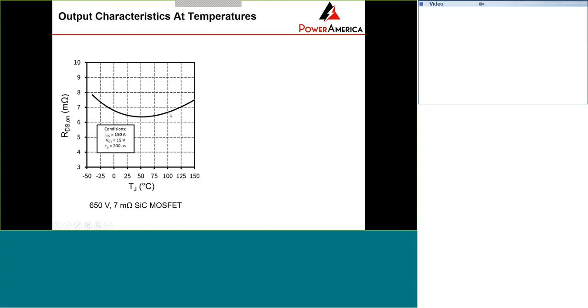And when we increase the temperature beyond room temperature, to 50 degrees C, the resistance increases again because the drift resistance increased and channel resistance reduced at high temperature. But overall, if you compare the resistance at 150 degrees C and room temperature, it is just increased by 15%. So the temperature coefficient of this device is very small compared to the high voltage devices, or let's say 1200 volts, normally 50%. 10 kV is even more.